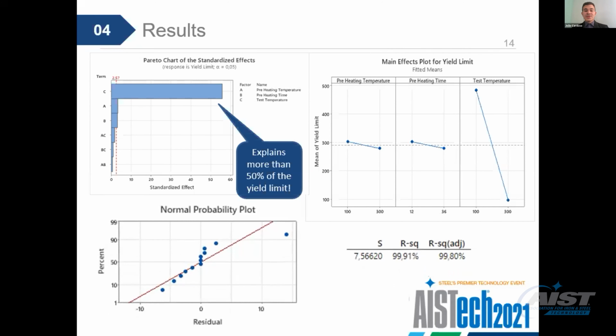These results show that the model is statistically significant, and we can see it through the R-squared and adjusted R-squared. These values are really close to 1. That means a good model. And as you can see in the normal probability plot, most of the residuals are right close to the normal line.